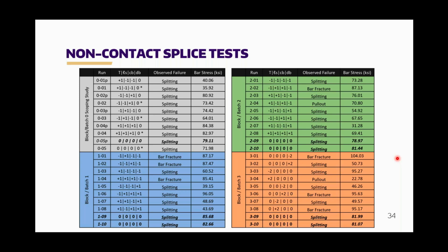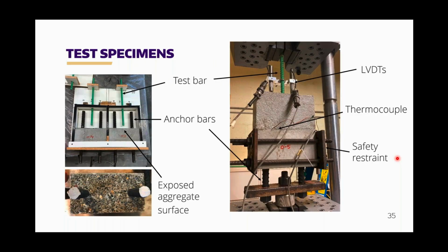To give you a picture of what these look like in real life, not just a figure, the top left picture is in the middle of the creation of this specimen. Those boxes were what was used as formwork. At the current stage of the specimen here, we have the number 8s embedded in the cementitious concrete. That's the existing concrete block that you see there. And then the epoxy bar is put in that formwork, and you can see the splice length for those particular specimens.